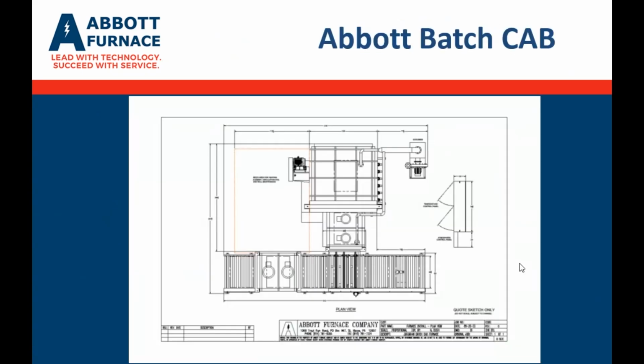So looking at a batch furnace, this is the top view looking down. At the bottom is the belt or the roller, the material handling. So the part, or the tray full of parts, is loaded. The part is then indexed over in front of the furnace. You can see some darker lines there, which are chains that would pick up the tray and index it into the first chamber you see with the two fans. That would act as a purge chamber where we're reducing the oxygen levels while that inner door is still shut. When the oxygen levels are appropriate, that inner door opens and the load is transferred into the brazing chamber. That door shuts and we go through our heating cycle.